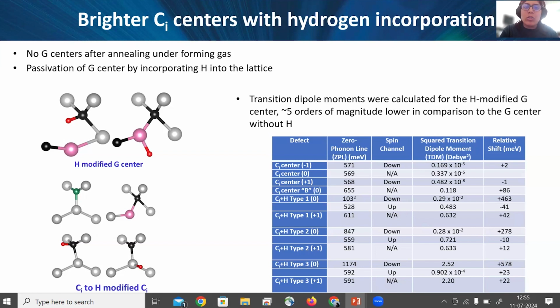And by doing that, you also form a new type of color center, which is a CI center. So you have a carbon in your lattice because you introduce it with the ion implantation, and now you have a hydrogen. When you have this hydrogen close to the CI center, the intensity that you measure experimentally increases by a couple of orders of magnitude. So by just making this small change of replacing inert gas with hydrogen-based forming gas, you can passivate this commonly formed G center while making a more interesting CI center, because the CI center not only can provide you a single photon, but also has a spin degree of freedom. So it is basically a spin photon qubit. So when we do this process, we can have the CI centers.